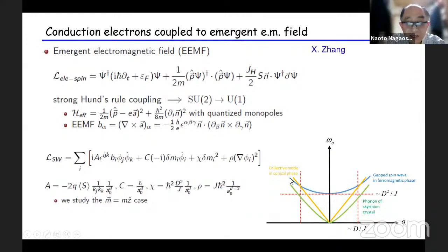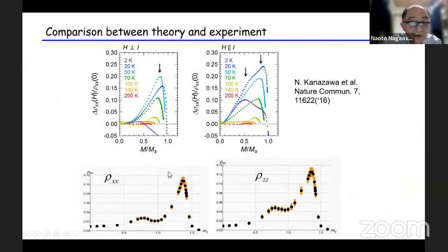So this spin wave is given by this spectrum. So under the zero magnetic field, we don't have a Berry phase given here because you don't have a small b field here. So then you have a k linear dispersion given by this. But under the magnetic field, this b field becomes finite, and then the spectrum will be split into the gapped spin wave and k square dispersions, skyrmion crystal phonons. So taking into account this fluctuation and plugging in this small a fluctuation, we can calculate the resistivity given by this as a function of the Mz.